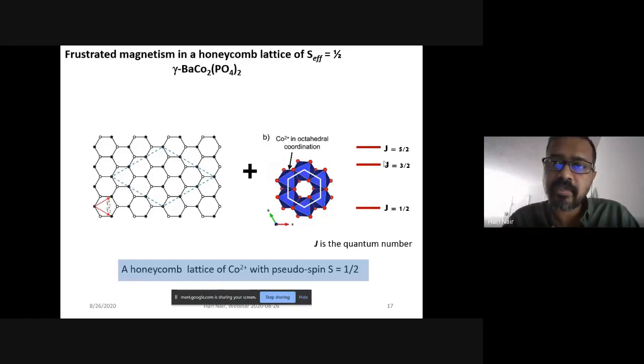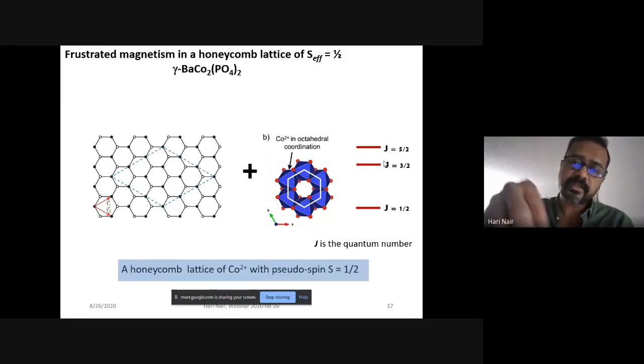Now, how come we have S effective equal to half? Because cobalt should have 3/2 or so spin. The effective spin half comes about because of the crystal field splitting. Because cobalt, if you look at the center, the blue figure, the cobalt 2+ is in an octahedral coordination of oxygen ions, which are shown in red. So the cobalt atom is sitting at a location where it is surrounded by the negative charges of oxygen in an octahedra. And this forms something similar to what you already know as the Stark effect. So it's a magnetic moment or an atom in an electric field.